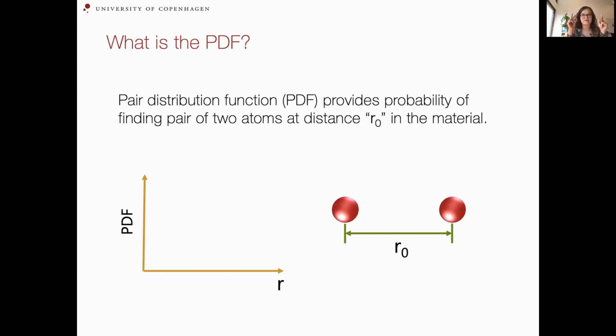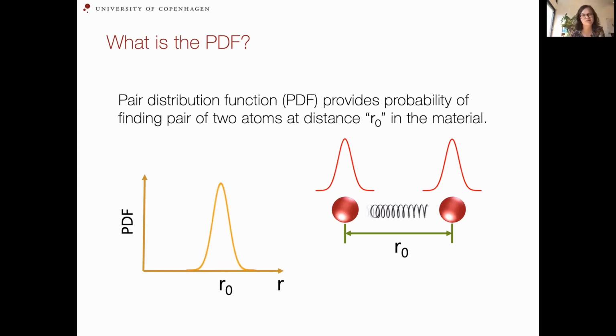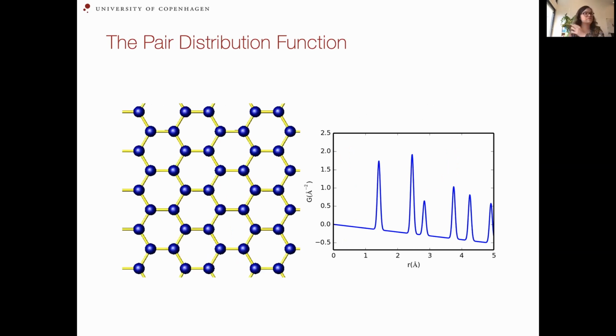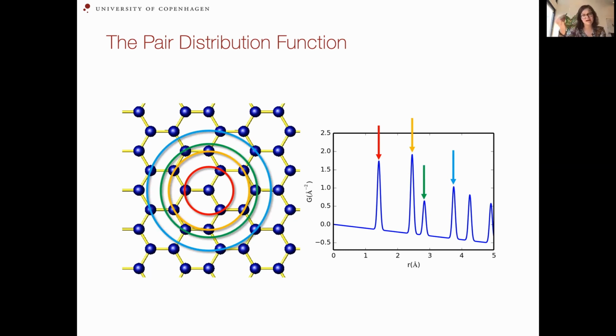Because imagine first I have a structure consisting of these two atoms, separated by a distance R0. Well, the PDF from this structure would give one peak in R at R0. And then probably my atoms would vibrate a little bit, so I would get a broadening of my PDF peaks, because it basically just represents a histogram of the interatomic distances that I have in my sample. And if we do it for a 2D sample, then I would see a PDF peak as the first interatomic distance here, and here, and here, and here, and so on. So it's a fairly intuitive way of analyzing scattering data.